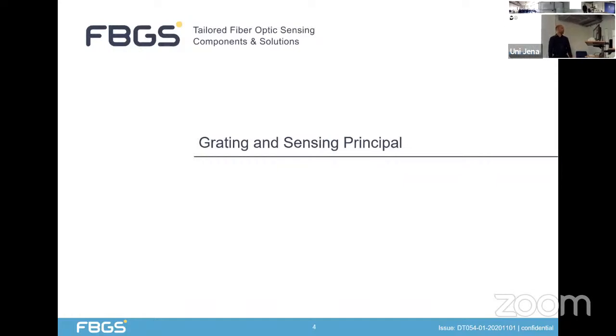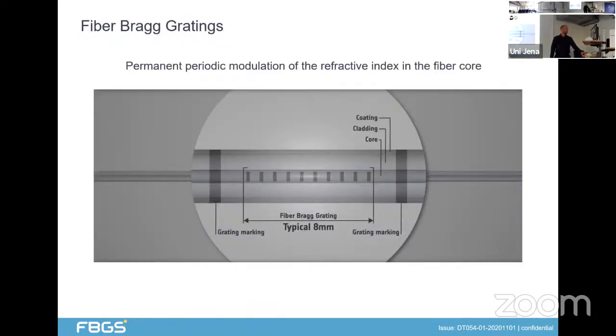In the next part, I will explain a bit the grating principle and how we use these fiber gratings for sensing. As you know, we use a fiber, typically single mode fibers with a core in the middle, then cladding surrounding that, and the fiber usually also has a coating which protects the fiber. A fiber optic sensor, or the so-called fiber Bragg grating, is a permanent periodic refractive index change of the core of the fiber. Typical fiber gratings for sensing have lengths in the range of 1 millimeter up to 10 millimeters. As the grating itself is not really visible after the production, we also mark the fibers so that we and later on customers can find the gratings back.